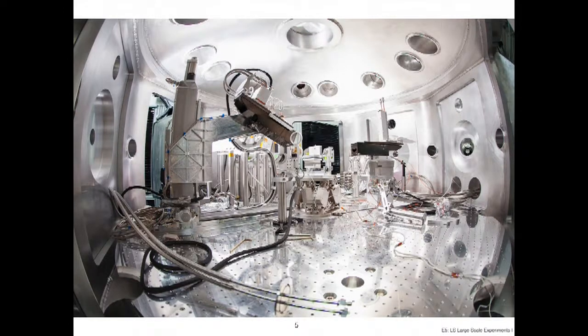Now, when users come in, it's a bit different than most of the other stations at LCLS. This vacuum chamber is generally empty. There's just a sample stage in the middle. Users come in, they put in drive beams, they route their optical lasers to the sample, they put all their diagnostics around it, and they essentially place the diagnostics they want. We have some stock diagnostics which they can use, and they're very frequently used, but sometimes they come with their own spectrometers to look at scattering, X-ray emission, or optical emission from the sample they create, and put that in there. So whatever fits within reason, we can place in this chamber and do an experiment.